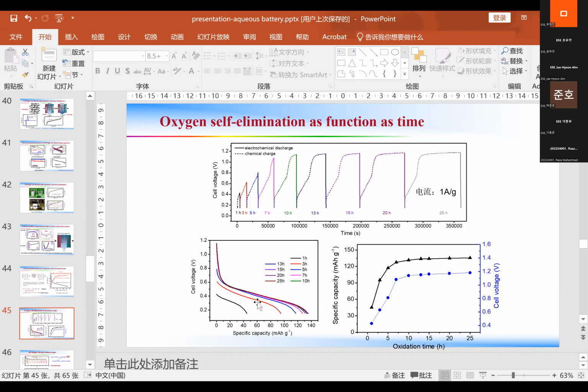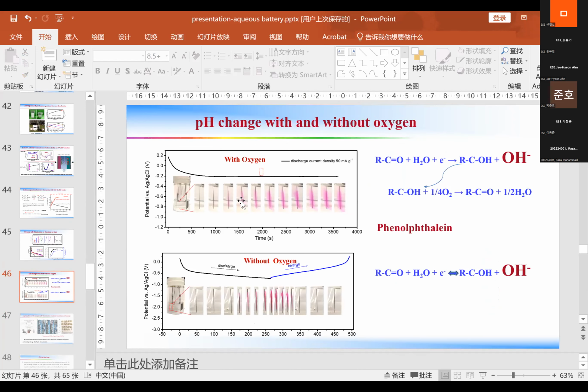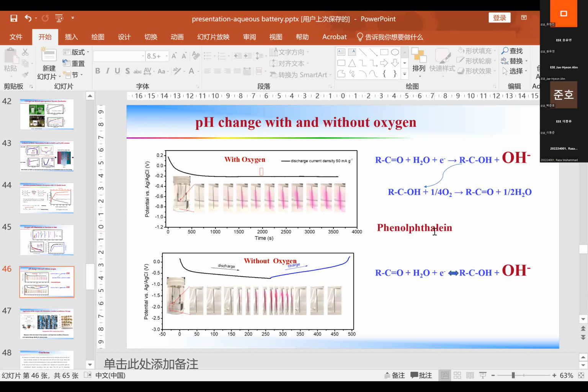You will see this is just 1 hour, and 1 hour after discharge, we stay in the oxygen atmosphere for 1 hour, and then for 10 hours. So over 10 hours, the capacity is the same as the electrochemical charge one. And then we see the oxygen. We use phenolphthalein as an indicator to check the pH value changes. With oxygen, the discharge process will produce OH, and this material will be oxidized by oxygen, and the OH concentration becomes bigger and bigger, so the pink color becomes much more pink.